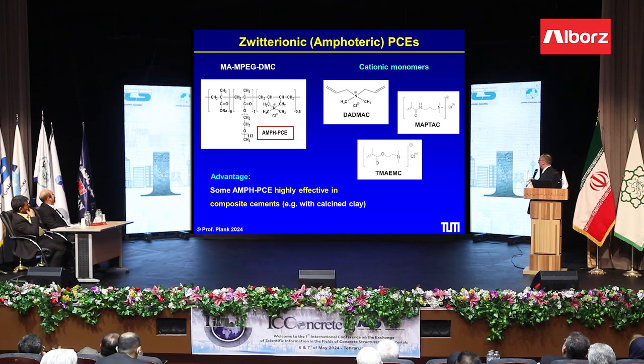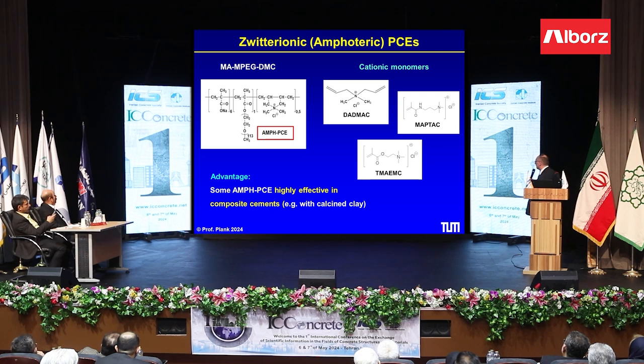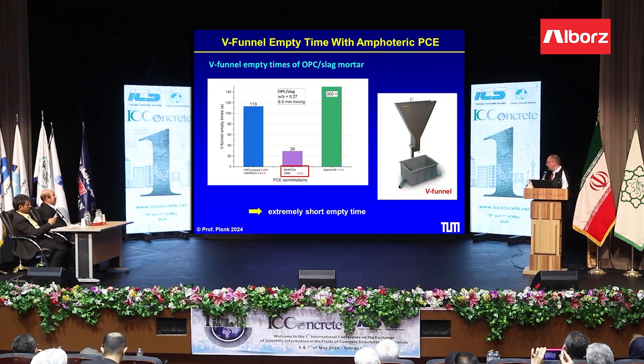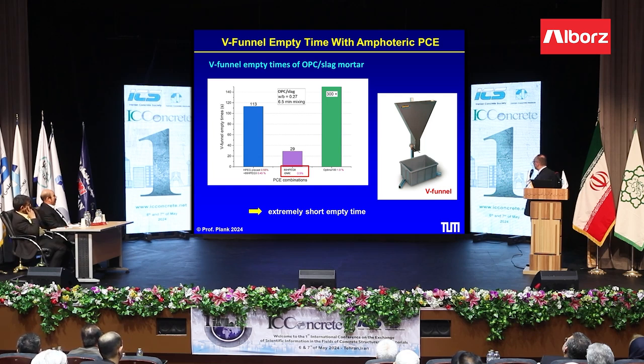Also recently we did quite some research on what we call amphoteric PCEs, where we also have a cationic monomer in the PCE molecule, so not only a carboxylate but also a cationic group, and these polymers are very interesting for high calcined clay blended cements, for example, and they also give very high flow speed, as we found in the V-funnel test. Here we had an OPC slag mortar, which we filled into the V-funnel, and the empty time was only 29 seconds with the amphoteric PCE. The conventional PCE took over 100 seconds, and another reference product took 300 seconds. So, like I said, with this very targeted molecular design, we can get very nice specific properties.